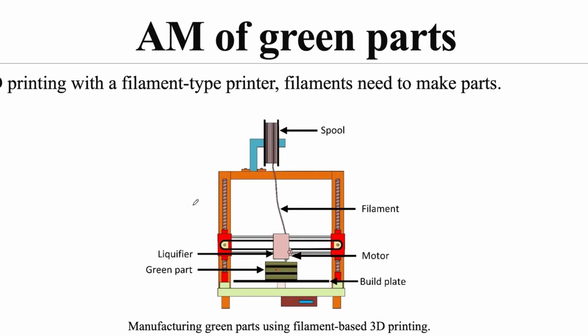When you are printing polymers, there is no metal in it. I'm just talking about FDM printing. When you are printing in ABS or PLA, there's no metal powder in it, so it doesn't matter whether the nozzle is hardened or not. But in this particular case, there is metal powder in it, and this metal powder will again and again rub against the head of the nozzle, and because of that, your nozzle will be worn out very, very fast. So you need to use a very hardened nozzle, a very special kind of nozzle. But other than that, you don't have to modify anything in the structure.